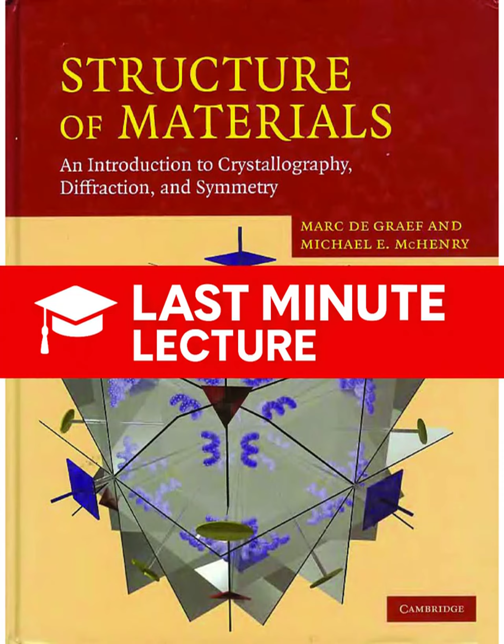But the moment we introduce aluminum, the charge game begins. Right. When an aluminum, Al3+, replaces the higher charge silicon, Si4+, the network develops a negative charge. It's often represented by the anion AlO2. So to maintain charge neutrality in the overall crystal, you have to incorporate additional large cations: sodium, calcium, potassium. They get incorporated into the vacant spaces within that 3D network. And this is the mechanism that creates the vast families of minerals like feldspars and, very importantly, zeolites.